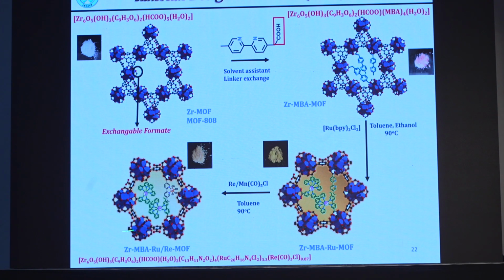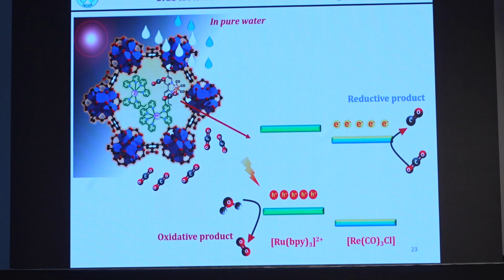Then I can put some kind of molecular catalyst, rhenium or manganese, here. So what I expect, because the MOF does not absorb in the visible light, the ruthenium bipyridyl will have the 3MLCT absorption. So 3MLCT, high excited state lifetime, it will go to the rhenium center or the manganese center to do the catalysis, okay? So let's see how it is happening. So this is the whole process I've described.